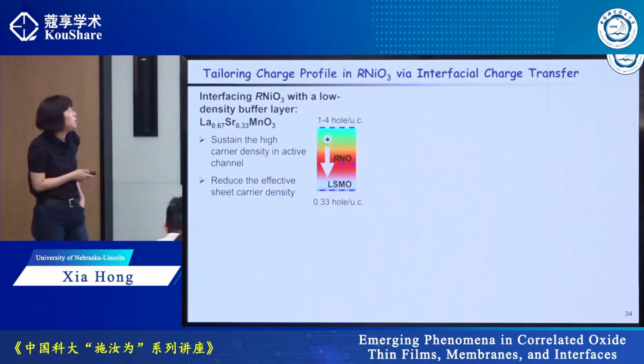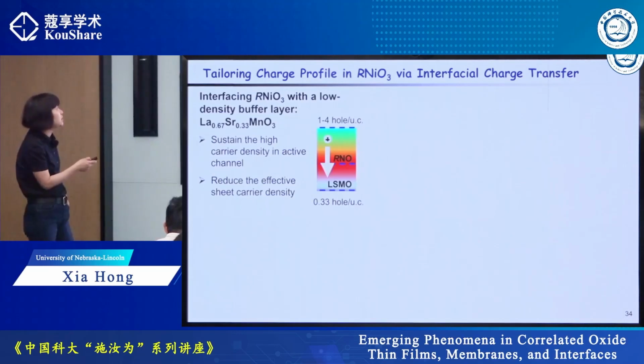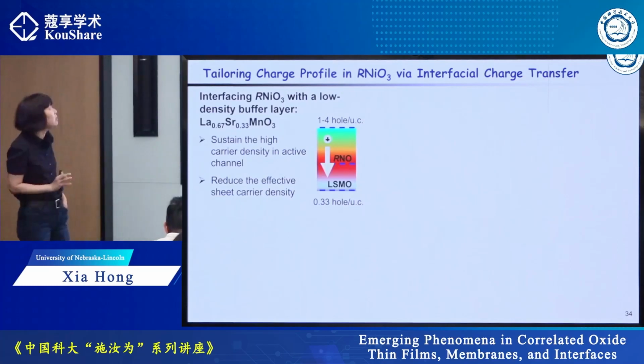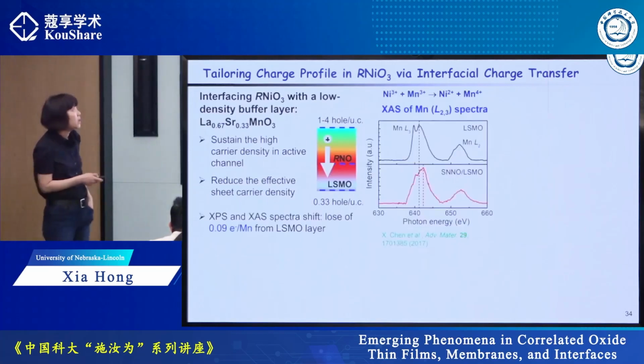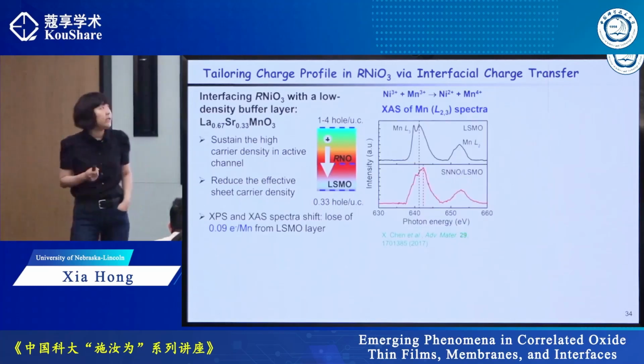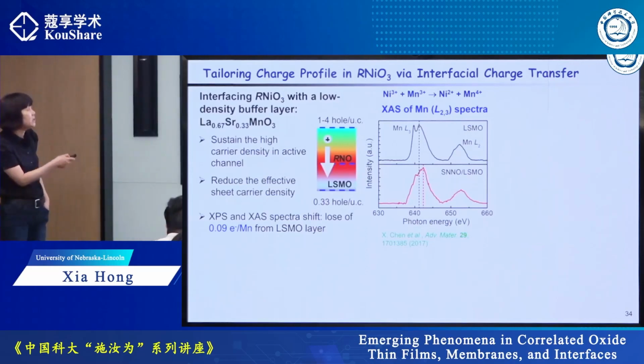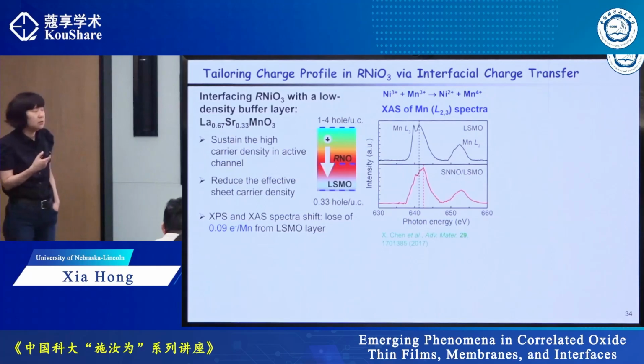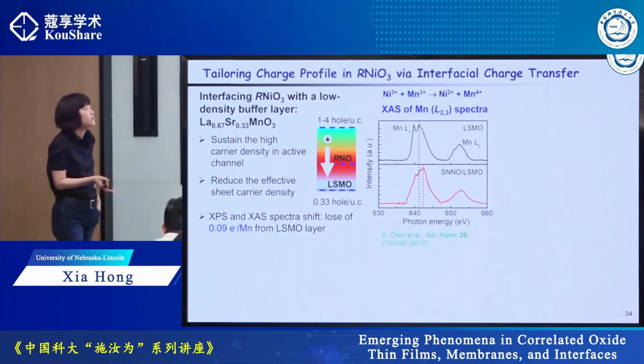So we thought what we can do is interface the rare earth nickelate with something that has intrinsically 10 times lower carrier density, such as strontium-doped lanthanum manganite. We have done XPS and XAS to study the bilayer systems to verify that indeed we have created such a tapered carrier density profile. You can see that there's about 0.1 electron per manganese transferred from LSMO to the nickelate, which means a hole transfer from the nickelate to LSMO.